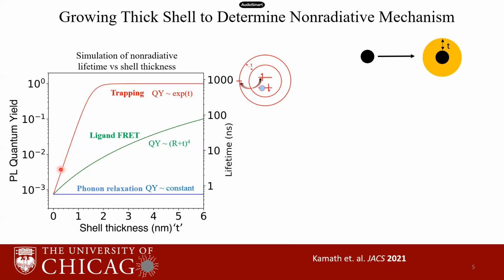The first mechanism, which is surface trapping, involves a quantum mechanical coupling of the electronic wave function with defect states on the surface. So as we grow a shell, we should expect the non-radiative decay to obey a tunneling behavior. That is, the PL quantum yield should increase exponentially with the shell thickness.